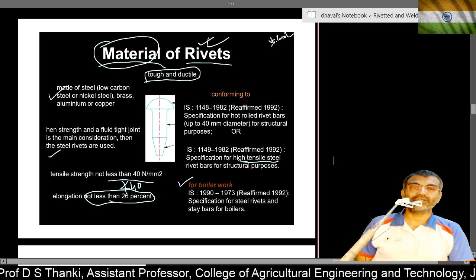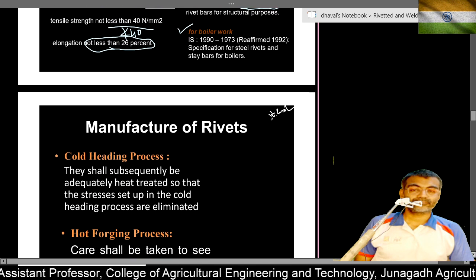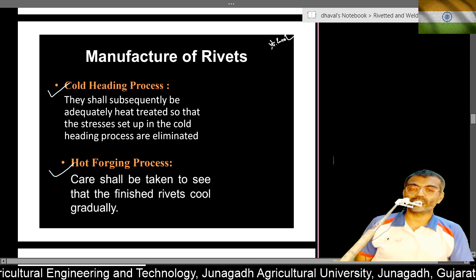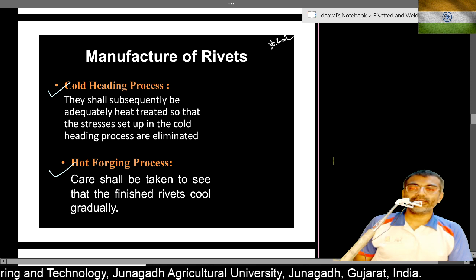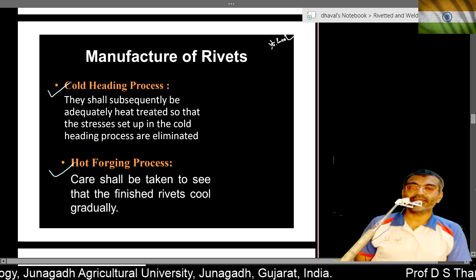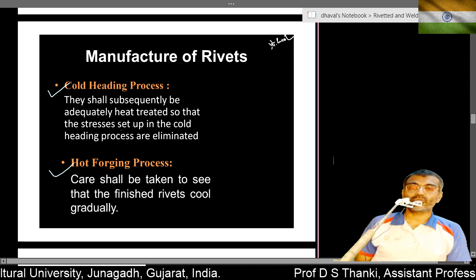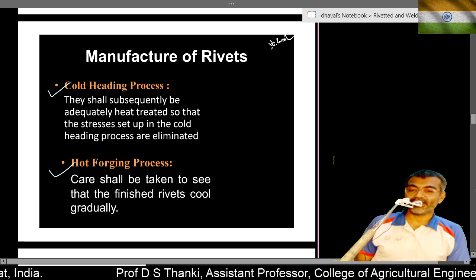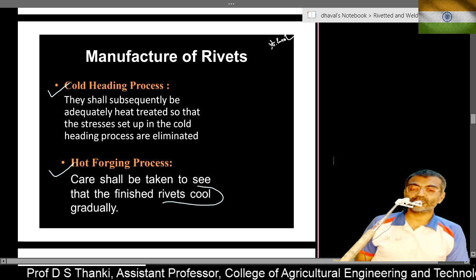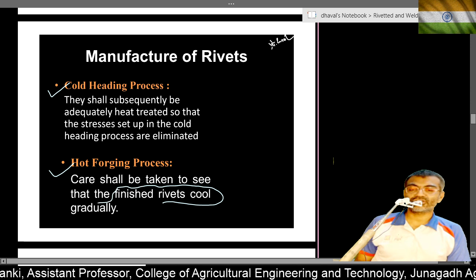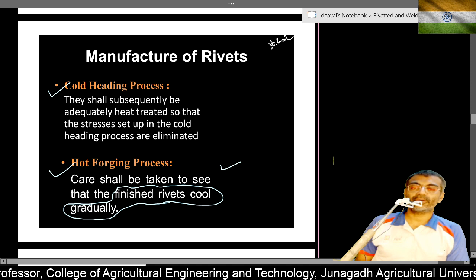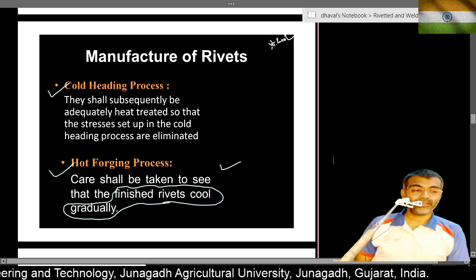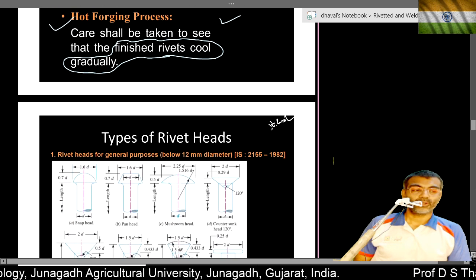For manufacturing of rivets, there are two methods: the cold heading process and the hot forging process. Rivets made by cold heading shall subsequently be adequately heat treated so that stresses set up during cold heading are eliminated. In hot forging, care shall be taken to ensure that the finished rivet is cooled gradually.